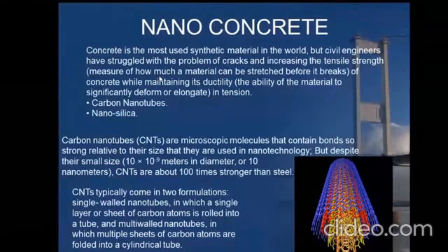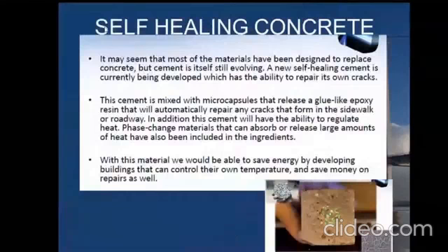The only major disadvantage in nano carbon is dispersion of these nanotubes, and now I think this can be overcome using a sonicator. So when you can disperse the nanotubes effectively using a sonicator, the strength of the nano concrete is again enormous. You can use it when you require a high strength concrete with lower cross sectional dimensions. This type of nano concrete can be used.